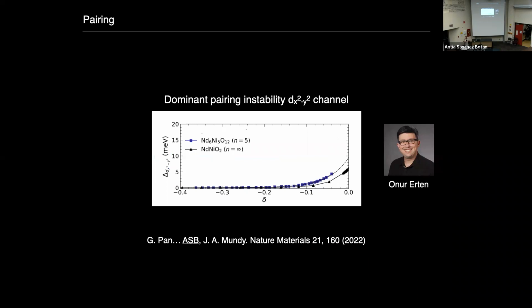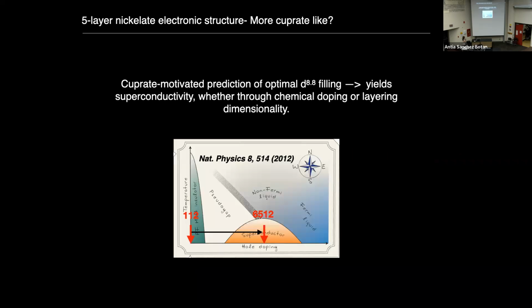Now, what about pairing? We haven't talked about that at all. We actually worked on that with Hanu Arita. And for the infinite layer material, already people using quite a few different methods had determined that very likely the dominant pairing instability was in the dx²-y² channel, like in the cuprates. And what we found is that the same situation stands for the 5-layer material as well. So all in all, this 5-layer nickelate seems to be kind of similar to the infinite layer compound, but a bit more cuprate-like if you want, in that you have this larger p-d hybridization and a reduced role of the rare earth states as well.